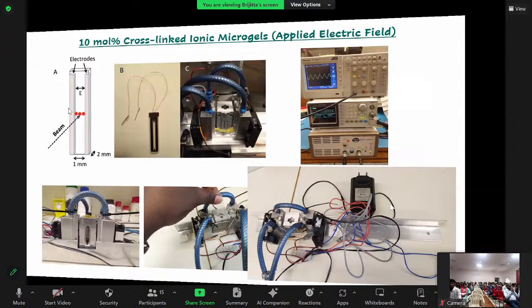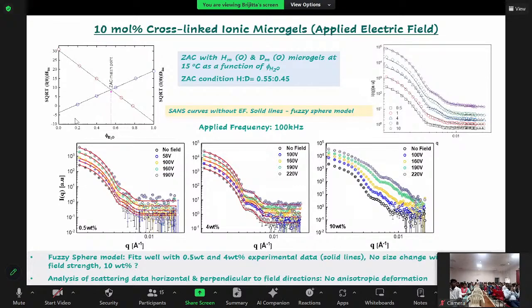You might have studied neutron scattering in your master's classes. First we determine the match point, and then after the match point we subject the particles to an electric field as a function of concentration, and these are called the form factors. We fit the fuzzy sphere model to the form factor, and from the fit we extract the size of the particles. The same sample, at all these concentrations, was subjected to field measurements, and you can see how the profile changes with electric field. Interestingly, we don't see much change, except that with field the intensity of the scatterers improves. Whereas at the higher concentration samples, you see that they develop a nice structure profile and they don't collapse onto each other.